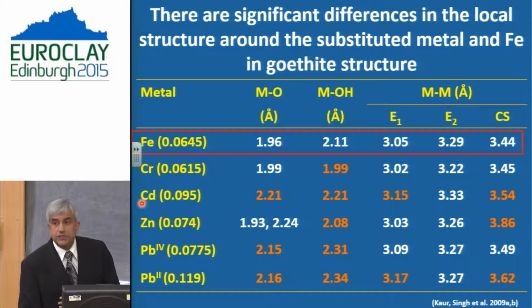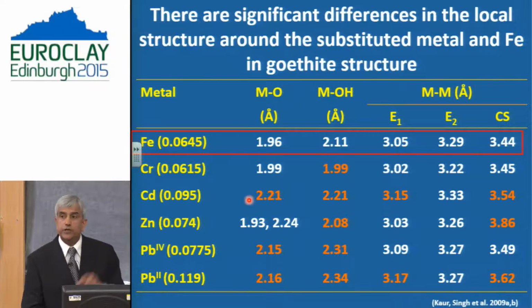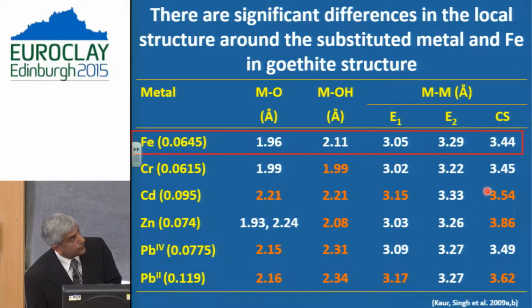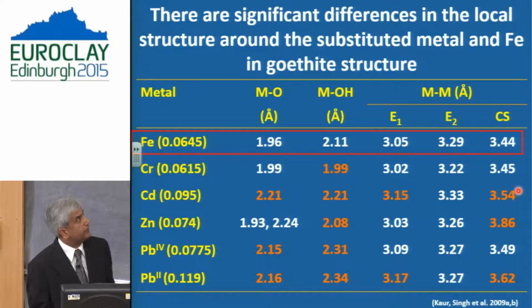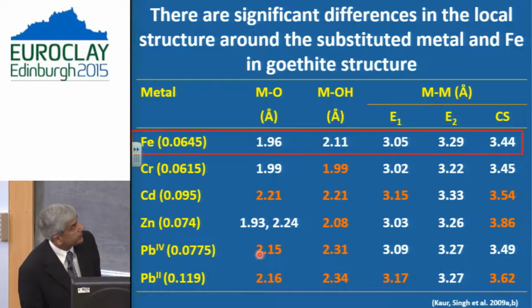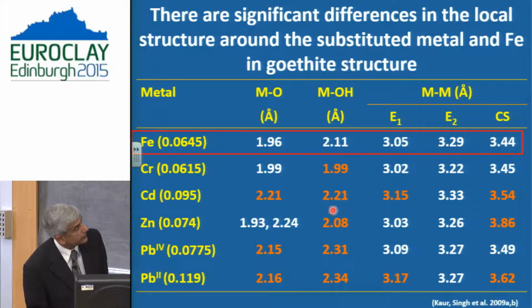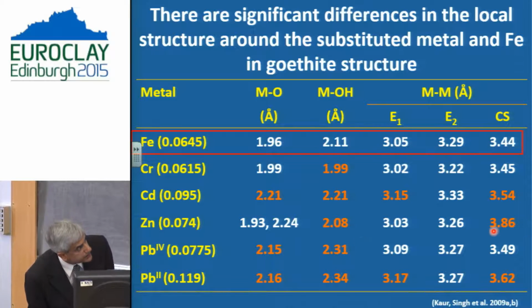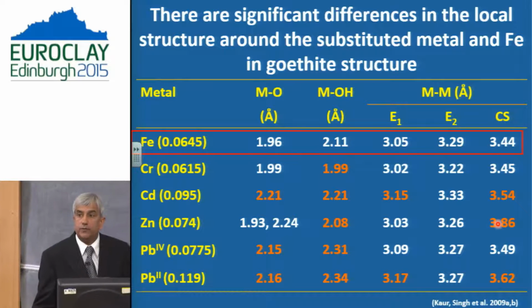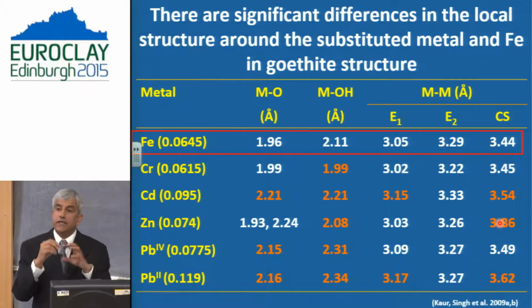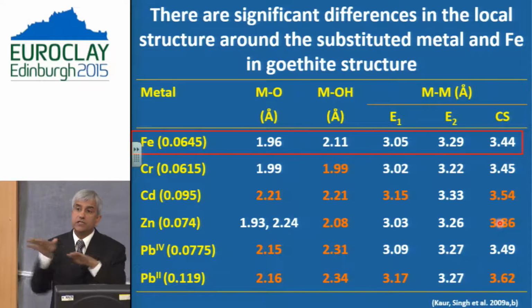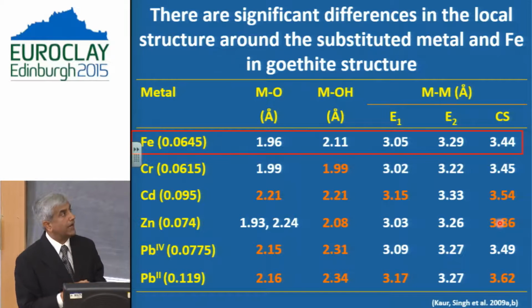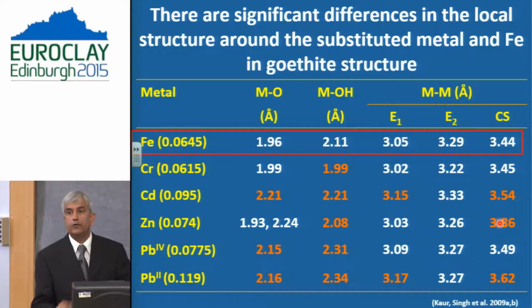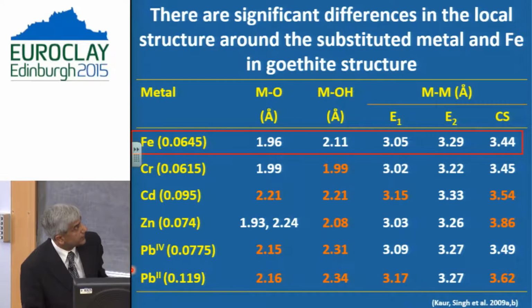In case of cadmium, which is much larger than ferric iron, you can see the distance between metal and oxygen hydroxyls have increased significantly. Also, one of the other metal-metal distances also increased. Likewise, in case of zinc, this distance has changed, and the metal-metal distance has become bigger. So what you are seeing is that as a result of the incorporation of these metals, you can see evidence for the distortion or slight changes in the local environment or local structure around the metal.